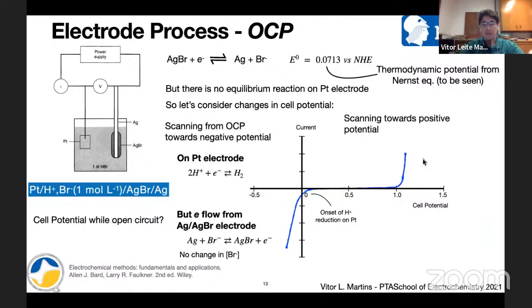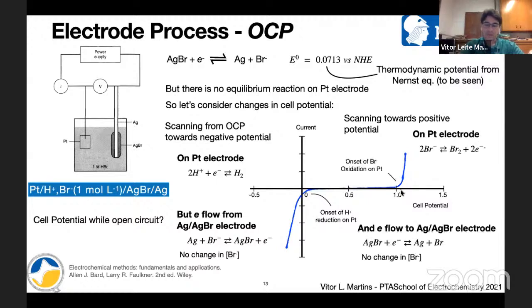So let's think about scanning towards positive potential. Starting from somewhere here that we don't know yet, you start to increase the potential positively, and then we have an onset of the bromide oxidation on platinum. So you see the oxidation of bromide forming bromine, and it's losing electrons here. All right. So this is happening on the platinum electrode, right? This is the working electrode in this case. So bromide is being oxidized on the platinum electrode,